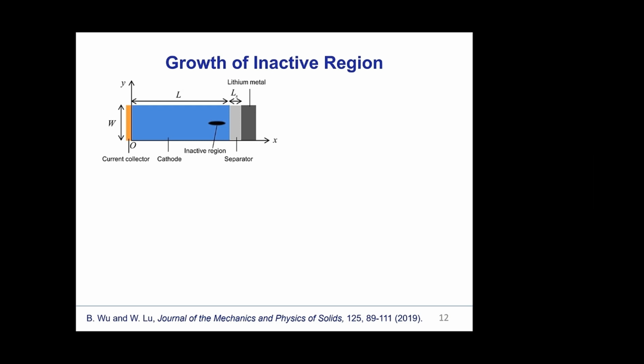Here we put an inactive region in the model. The inactive region is similar to other regions mechanically, only that the material in the inactive region does not participate in the electrochemical reaction. It is not a crack, so it has not received much attention before.